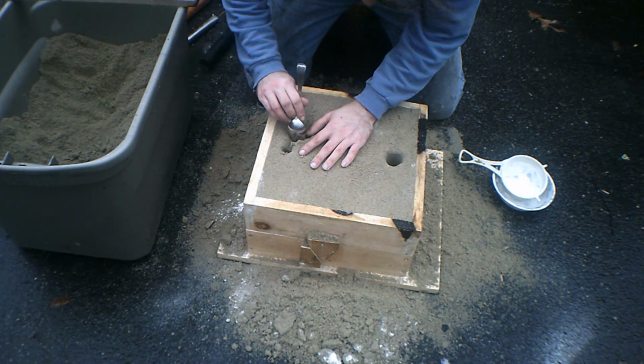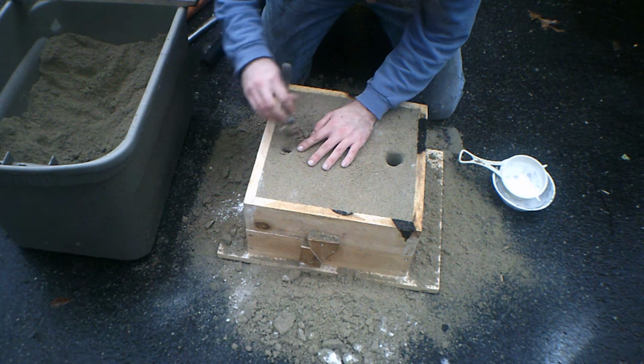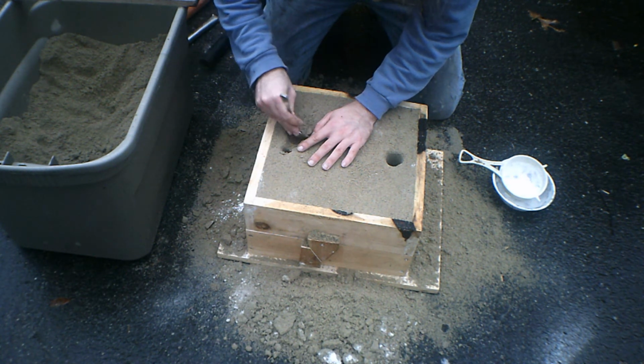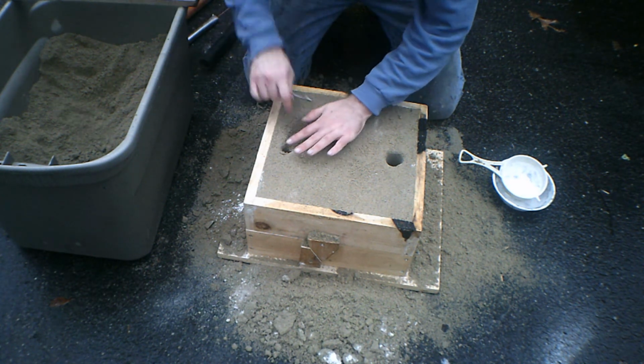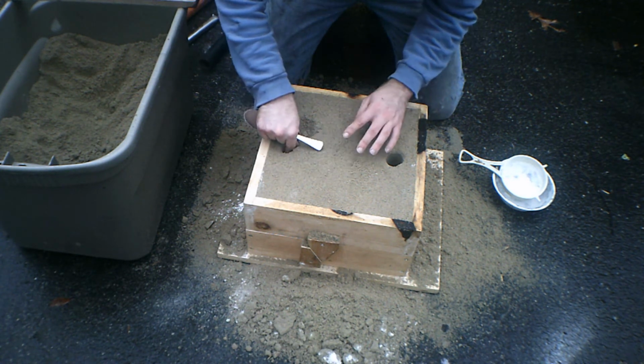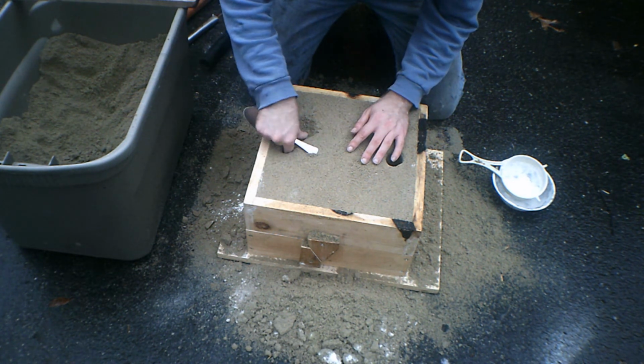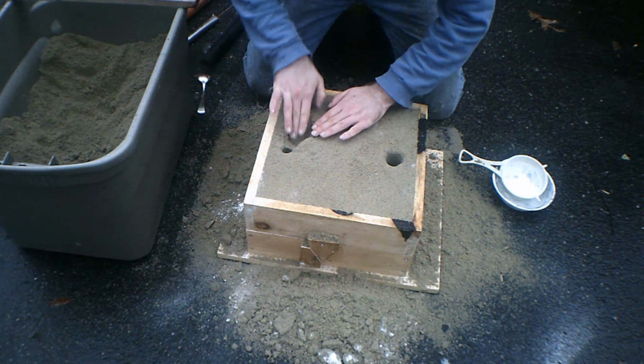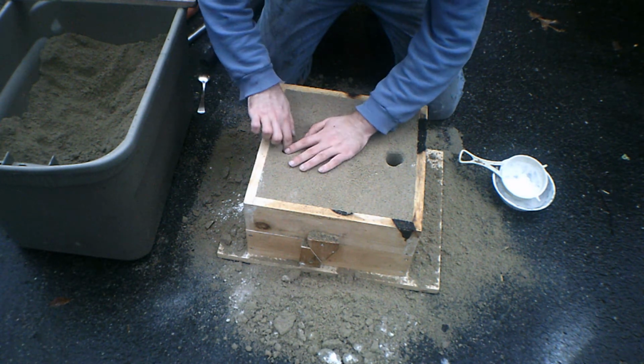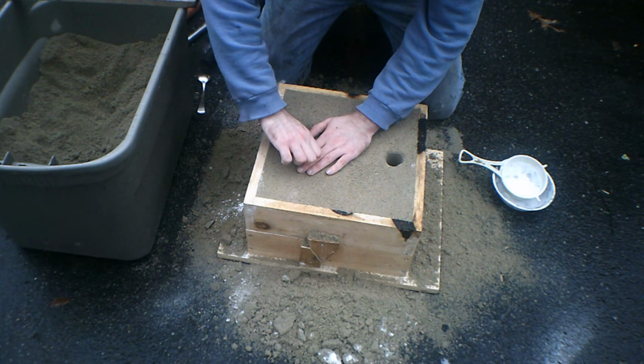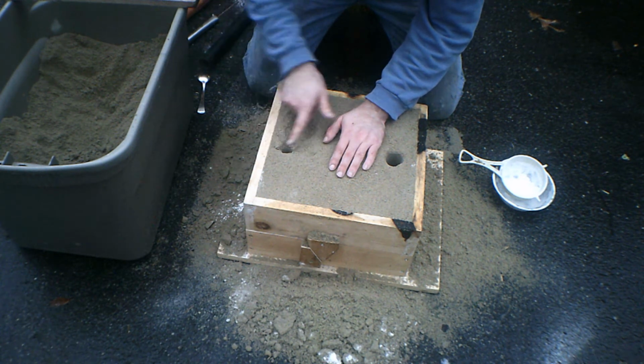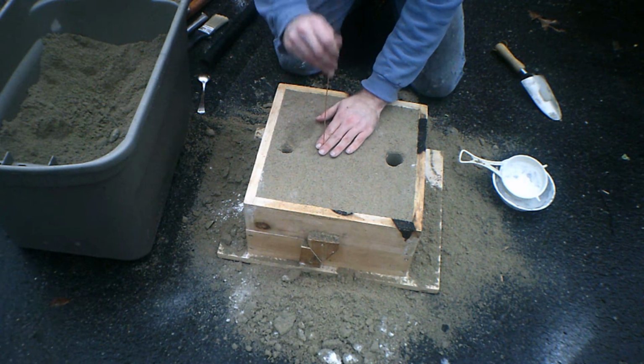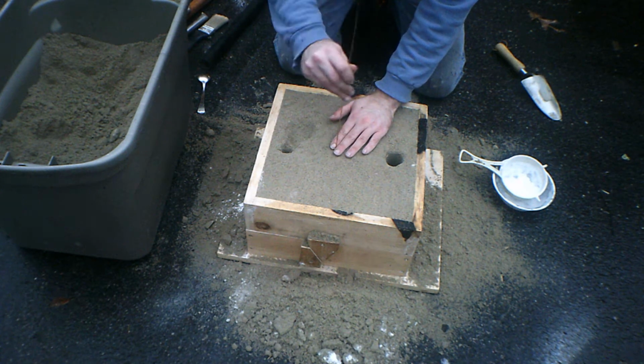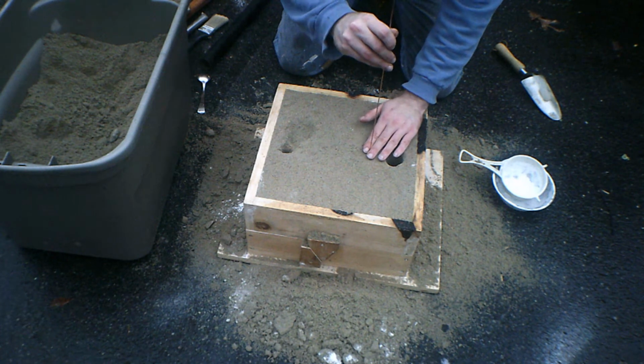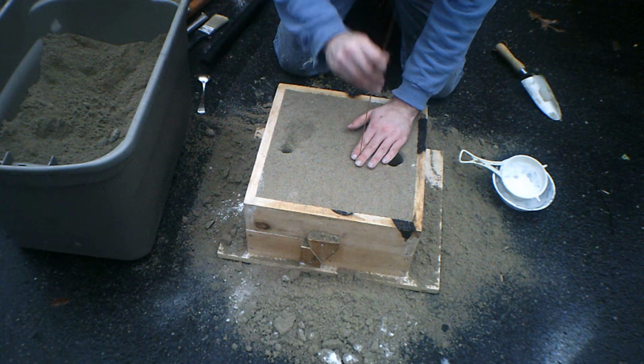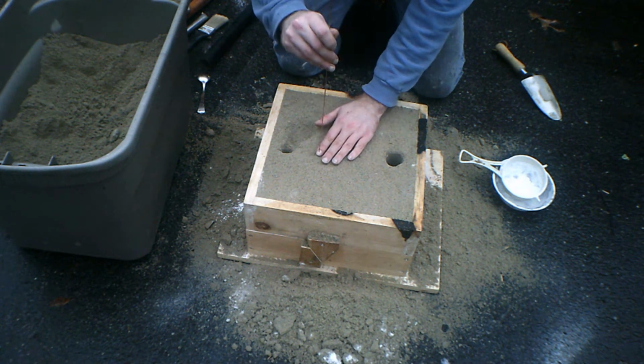The wonderful part about sand casting is that you can alter the sand as you need. Having a solid piece to form around is not necessary. Just remember that every time you alter sand, you have to press it back down again so nothing loose remains. Now the final step is using a piece of wire to form vents. Steam will be generated when you pour molten metal into sand mixed with water, so the steam needs somewhere to go, otherwise the entire thing just becomes weaker or makes bubbles in the surface of the finished metal part. So using a vent wire takes care of that.